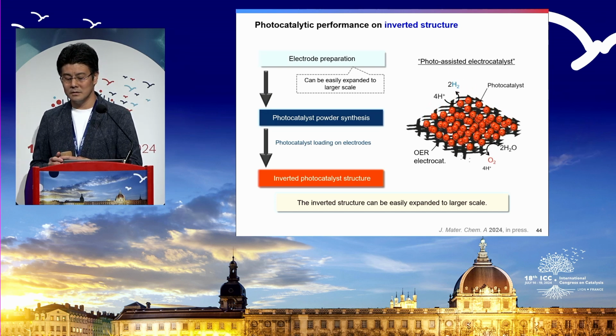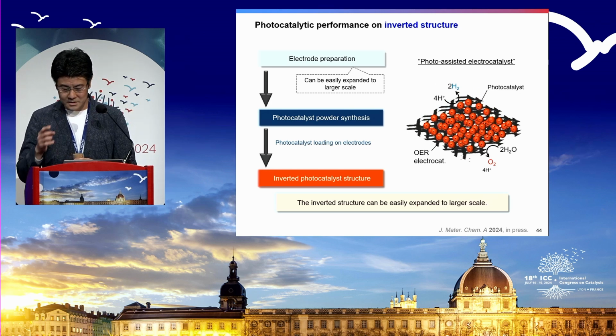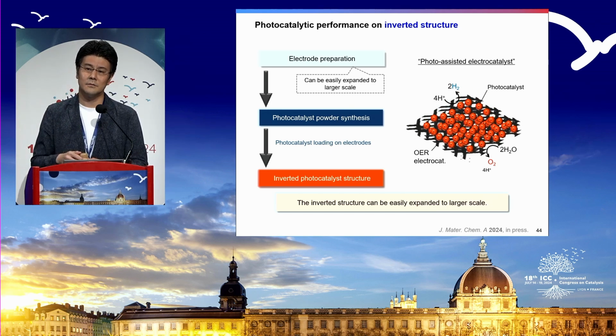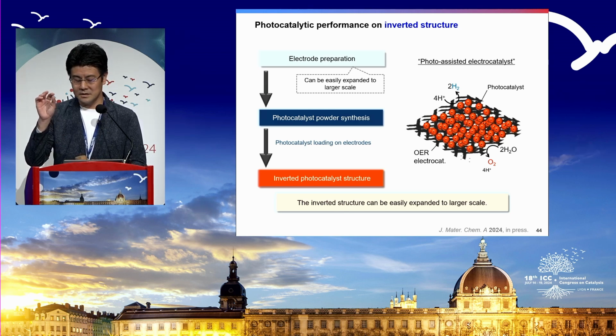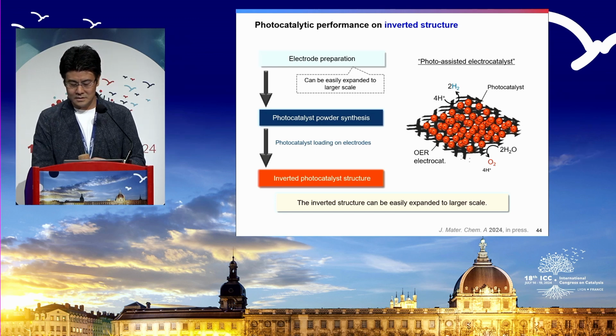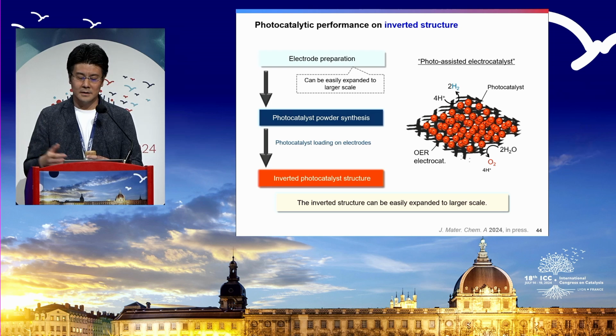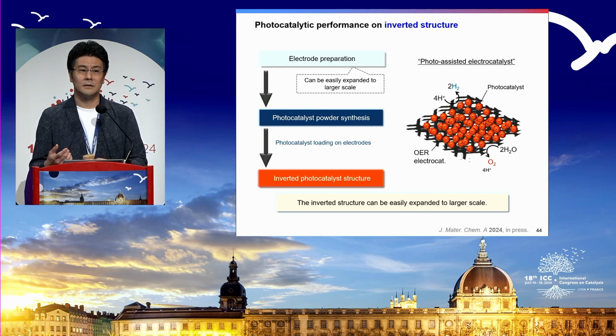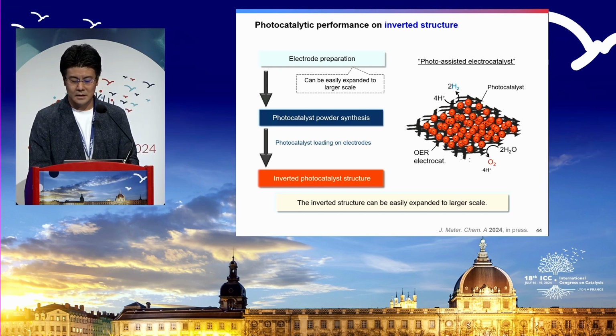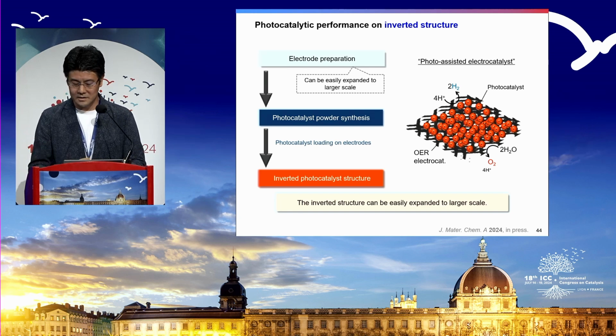Then you decorate this with the powders. This is already decorated with the hydrogen evolution side. Hydrogen evolution is much more efficient, with less overpotential, so you can minimize the quantity, so you can directly put it on this powder system. In this way, we hope that we can improve further toward a solar to hydrogen efficiency of 10%. Right? We need to start thinking about what is the quantity that is required for this electrocatalyst side, or co-catalyst, you call it.